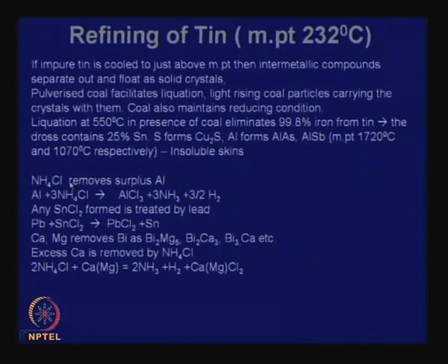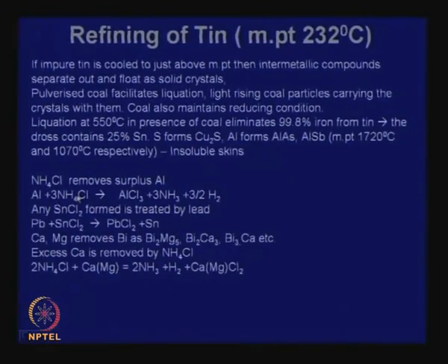Then this comes to pure chemistry. In that impure tin, we can add ammonium chloride to remove surplus aluminum that we have added. We may have added too much aluminum. Aluminum reacts with ammonium chloride to produce AlCl3 vapor, ammonia and hydrogen. They are all gases. Any SnCl2 formed is treated with lead. If during this treatment with ammonium chloride it produces SnCl2, then by adding lead we can recover tin, and the lead will form lead chloride. These are all chemical steps.